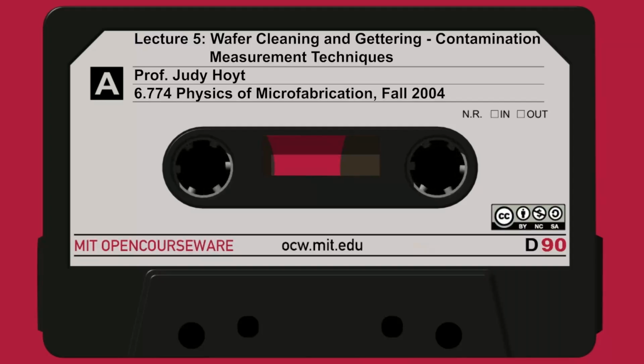So you could give someone familiar with it this data, and they could plot for you the density of traps in the band gap at that interface between silicon and silicon dioxide as a function of the energy in the band gap. And you can see it has this familiar U-shaped profile. In the center, it has some number, mid-gap that's typically 5 times 10 to the 10th traps per square centimeter. As you go closer to the edges, it goes up dramatically. But this is a way by CV of measuring DIT or QIT.